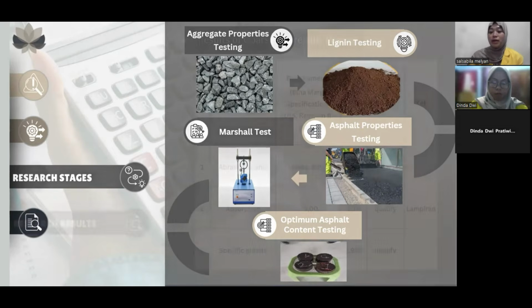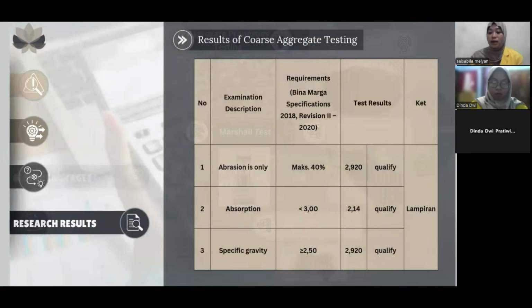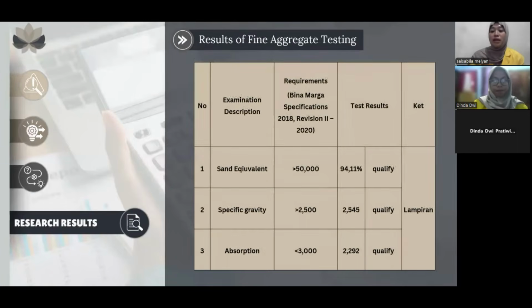The coarse aggregate test shows good results. All parameters meet the Bina Marga 2018 standard. Absorption, abrasion and specific gravity values all pass the requirement. For fine aggregate, the results are also good. Sand equivalent is 94.11%. Specific gravity is 2.545, and absorption is 2.292. All parameters pass the test.